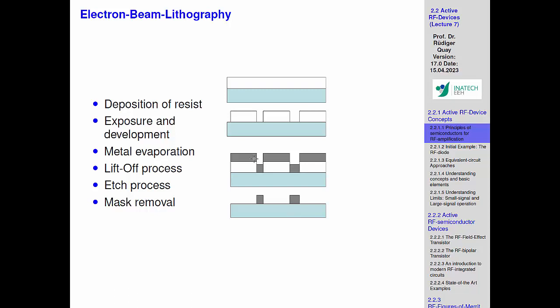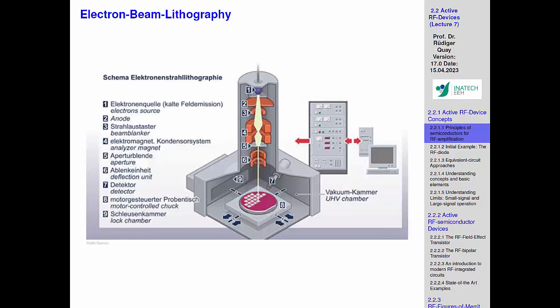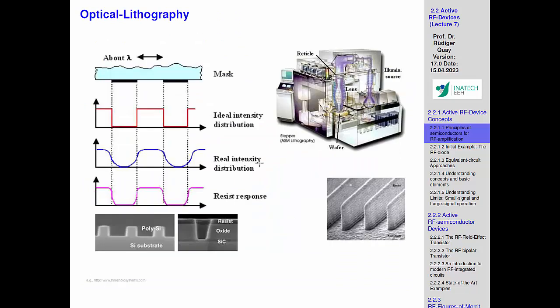So this is a very nice structure, but when you do it in reality, for example, if you remove the resist after this evaporation, what you don't want is that there's a fin going up here just on the side. These are all the physical problems you then have to solve. This looks very nice in theory, that you say, I can do these blocks. In reality, you always have to prove, and this is where we are spending most of our time, that these edges are really edges. And you see also there's a hole drilled, and it's not perfectly rectangular, because already removing stuff out of a hole is a big problem, and that's not something which works easily.